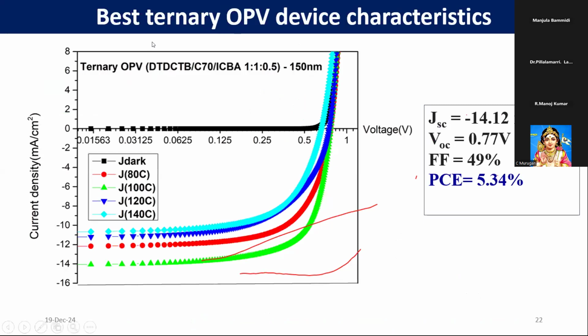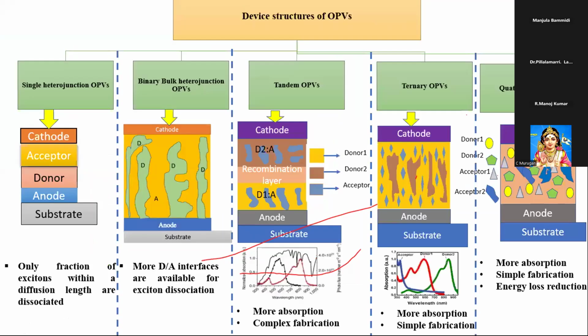Ultimately, we tried different concentration ratios and different thicknesses. At the concentration 1:1 to 0.5 and 150 nanometers, we were able to get 5.34 percent. This is the highest power conversion efficiency we have achieved with this ternary OPV device structure. If you see the advancement of organic photovoltaic cells from single heterojunction to quaternary, this is the advanced device structure.